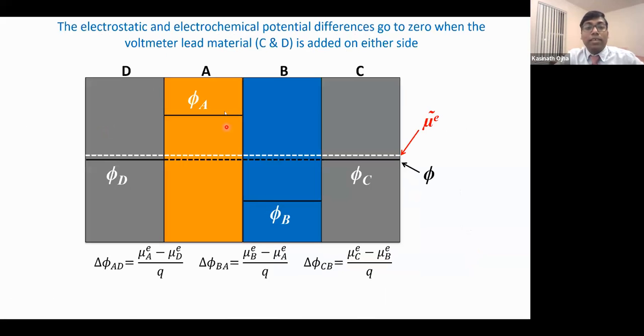Let's put it there. So if we connect a voltmeter to these two metal systems, we add one connector, basically one metal here, that's D, and then another connector, another metal here, C. Let's say those are two different metals. Then we work similarly as with that AB interface. So we now have the DA interface, then the AB interface, and then the BC interface. Now, if you do the same math that I did on the previous slide, we get an electrostatic potential difference at equilibrium at those three interfaces, and they are simply chemical potential differences. And if you calculate the total electrochemical potential difference over all three interfaces, you add all three and rearrange, and they actually cancel out each other. So you measure a 0.